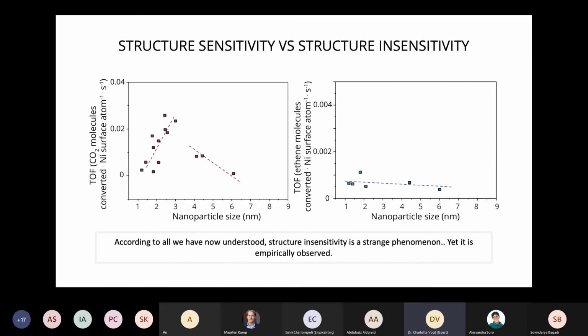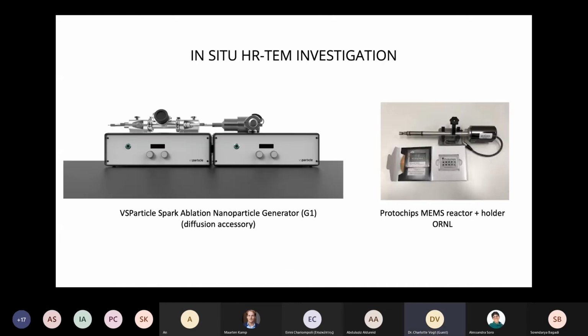So it's actually very, very interesting that that was empirically observed. So we went ahead and we tested again. We took our catalytic nanoparticles. We actually synthesized even more and tested in CO2 hydrogenation. We indeed still saw this structure sensitive effect. And we also tested ethene hydrogenation, which is a classic example, often studied in literature, of a structure insensitive reaction. And we see that the order of magnitude span, let's say, that this catalyst undergoes is much, much smaller. So we do, in fact, empirically observe structure insensitivity.